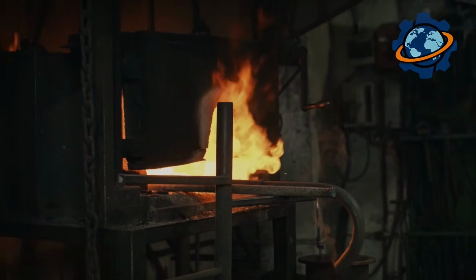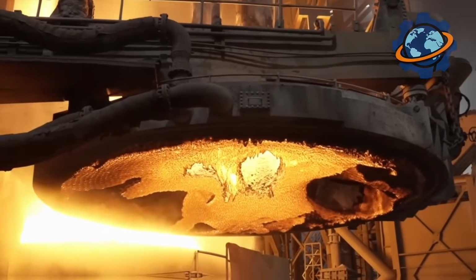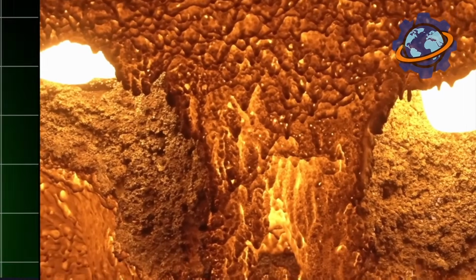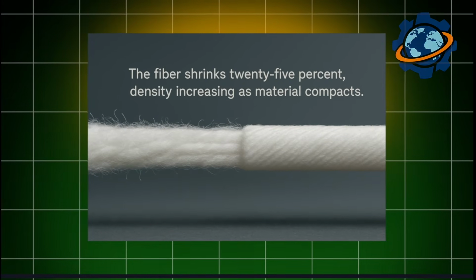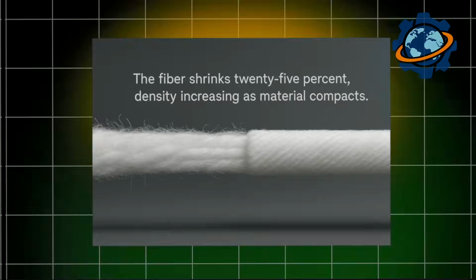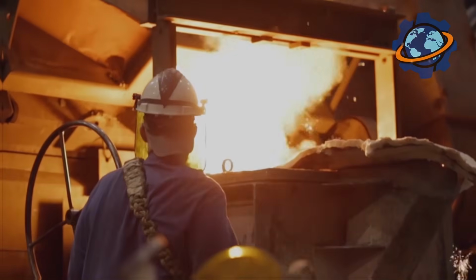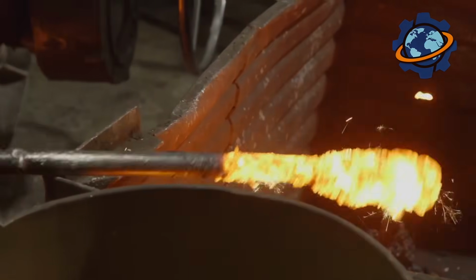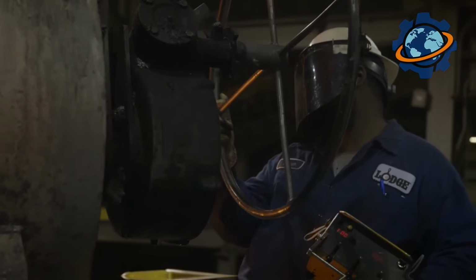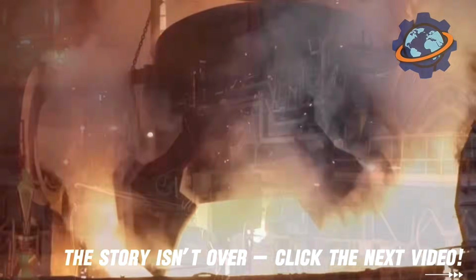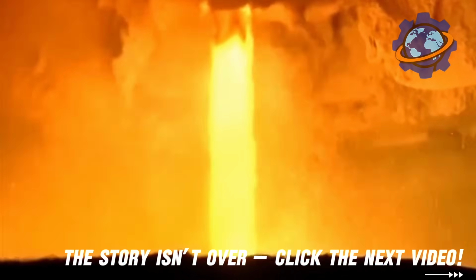The process occurs in stages. First, furnaces heat fibers to 2,700 degrees, driving off 90% of non-carbon atoms. The fiber shrinks 25%, density increasing as material compacts. Second stage furnaces push temperatures to 4,000 degrees for graphitization, the process aligning carbon atoms into perfect hexagonal sheets stacked like microscopic playing cards. This crystalline perfection gives carbon fiber its extraordinary properties. Processing takes 3 hours, crawling through furnace sections totaling 1,000 feet long. One power interruption, one oxygen leak, and fibers oxidize catastrophically, burning like magnesium flares, destroying millions in equipment.